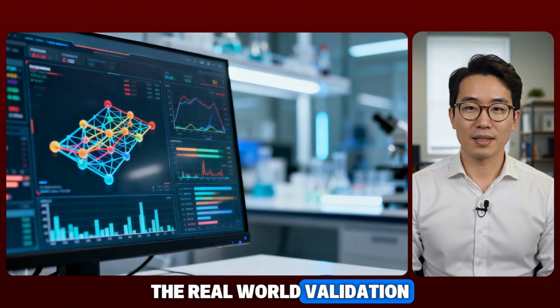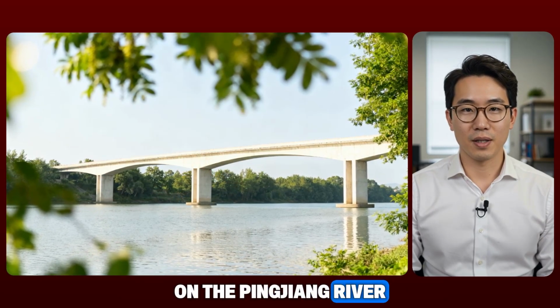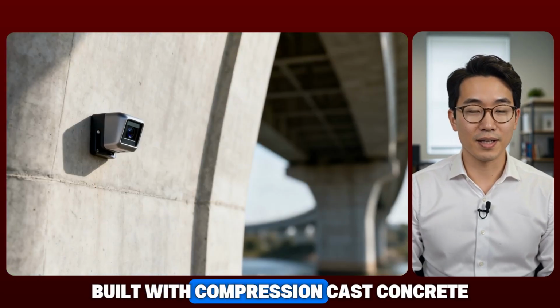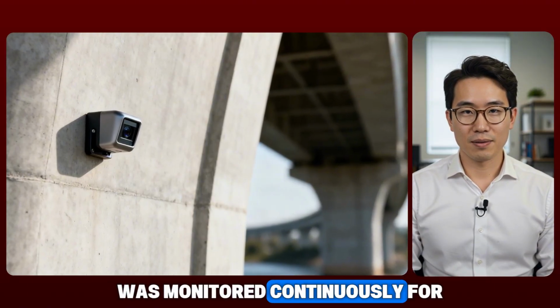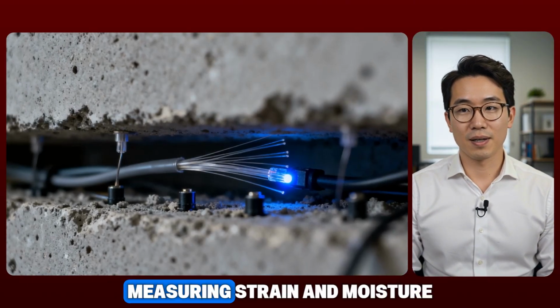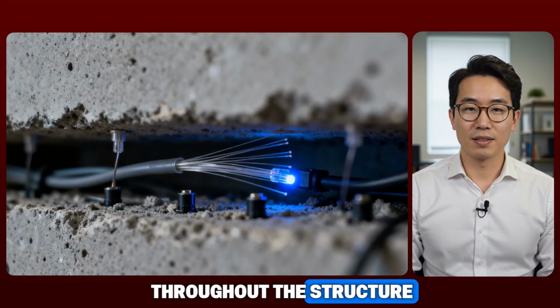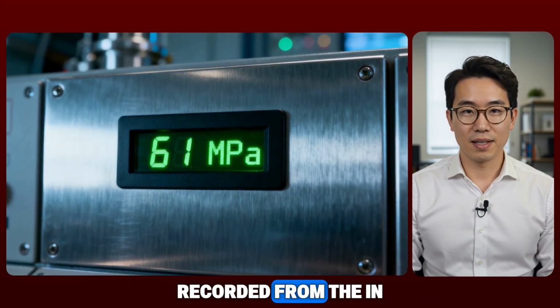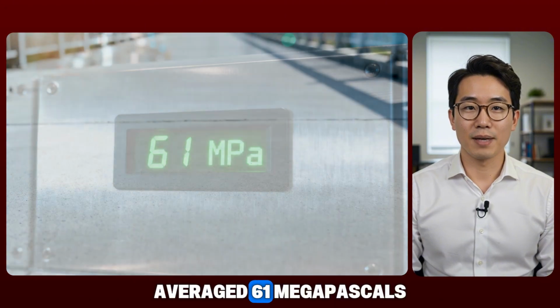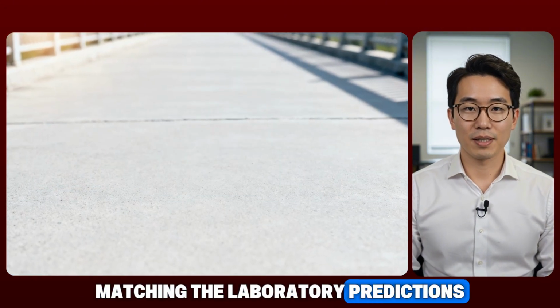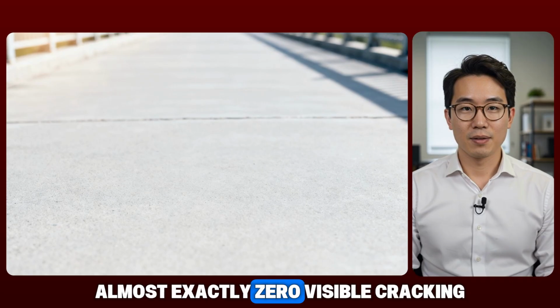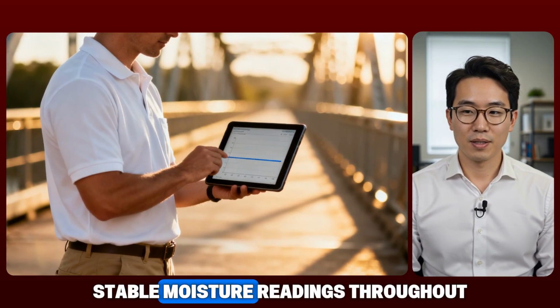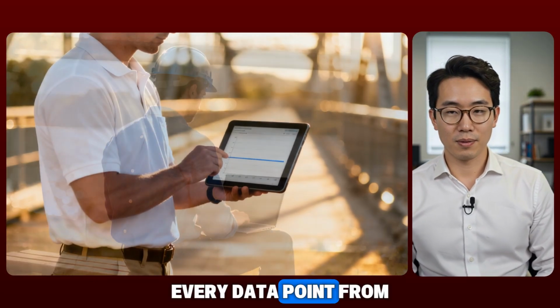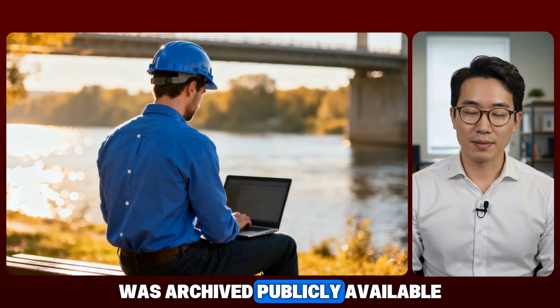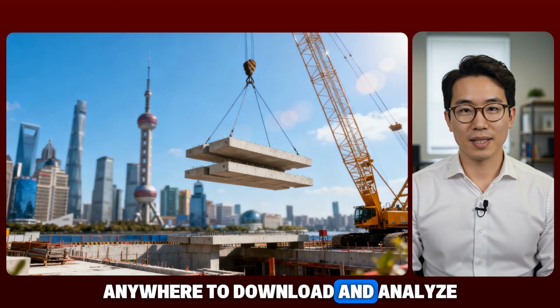The real-world validation that preceded all of this corporate activity was critical. On the Pingjiang River, 150 meters of bridge deck built with compression cast concrete was monitored continuously for 12 months using embedded sensors, measuring strain and moisture throughout the structure. The compressive strength recorded from the in-place material averaged 61 megapascals, matching the laboratory predictions almost exactly. 0 visible cracking. Stable moisture readings throughout. Every data point from that year of monitoring was archived publicly, available to any engineer anywhere to download and analyze.